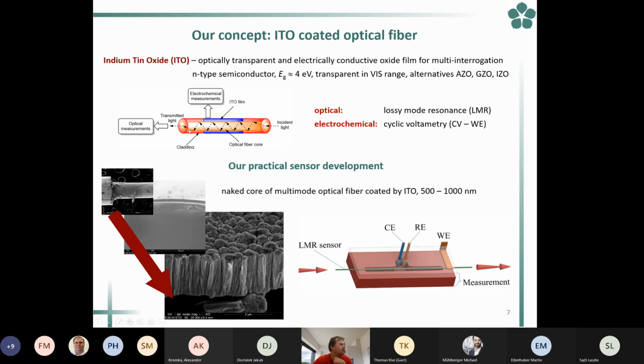We employ an optical fiber, which is able to combine the optical and electrochemical ways of detection. How is it done? For the optical detection, we can use the so-called lossy mode resonance. It can be induced by the optical fiber if it is coated by some suitable film. In our case, it is indium doped tin oxide. And actually, you can see it here. This is the fiber. The optical fiber is rid of the cladding. Here you can see the film that we deposit. Here is the bigger magnification.